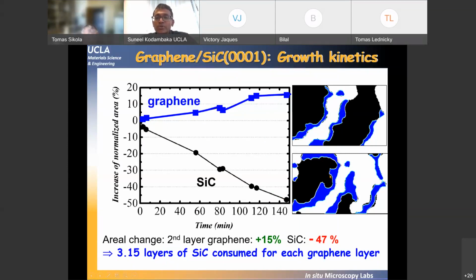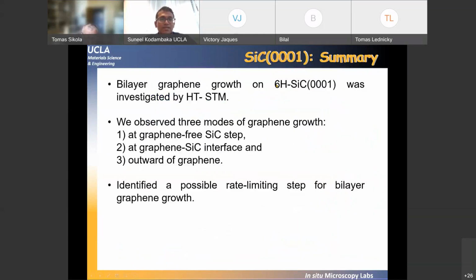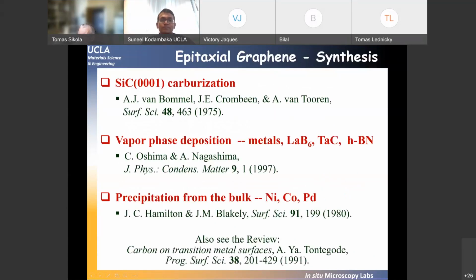And we've also looked at the atomistics of how this second layer graphene grows, and I will not go into any of those details, but we observed 3 different modes of graphene growth at the graphene-free silicon carbide steps, at the silicon carbide graphene interface, and in front of graphene. And based on these, we've been able to identify a rate-limiting step for how bilayer graphene grows on silicon carbide surfaces. Now let me come to the more common way of graphene growth.